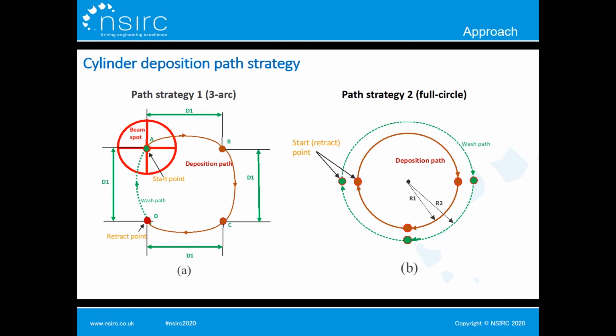Currently, there is numerous research about wire deposition on a straight line path, but still very limited reference about circular paths and cylinder building. Since there are complex phase change and wettability problems involved, I need to make sure that the melt wire can be collected in a small circular path and successfully build up a cylinder shape like a single rivet. So at the beginning of this project, the first experiment I need to conduct is a feasibility study of wire cylinder deposition on the metal substrate.